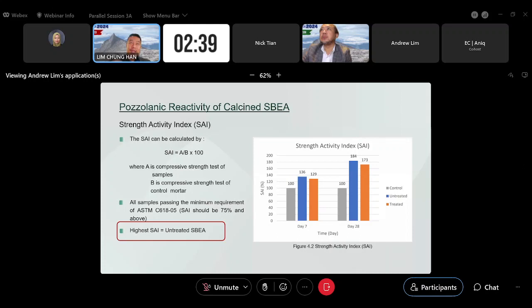Now, when you try to improve the performance of pozzolans using calcination, you have to be careful with the temperature you use. Every pozzolan has an ideal temperature at which you activate or treat it. Certain pozzolans you're looking at about 500 degrees Celsius, some 700 degrees Celsius. If you go over this temperature, you reduce the reactivity of the pozzolan. So the temperature range is very important. In this case, I probably used the wrong temperature because I only investigated one temperature, 700 degrees. I should have done one for 500, maybe another one for 600. Then I may have gotten an improvement in strength. So to answer your question, I didn't go for the correct temperature, basically. Okay, thank you very much.